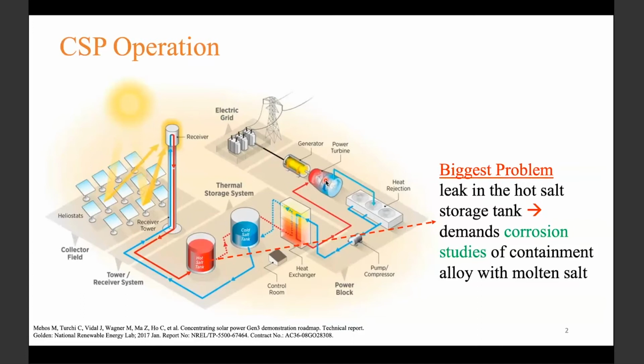So yes, it appears very neat and simple, until we recognize that in this process, we have created a potential volcano that can spout hot salts with temperatures above 700 degrees centigrade, once the hot salt corrodes and ruptures the metal alloy container. And I believe that after learning this, nobody of us would prefer to have it in RPI or be near such a plant.